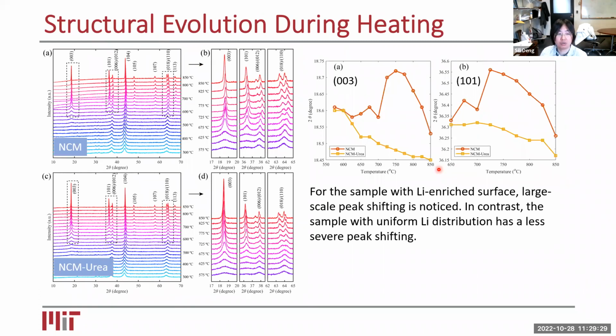We don't need to really go into the details, but this is to demonstrate how, after we utilize this method, the end product is sensitive to temperature. Because the whole reason for us to design this process is to push us to a higher temperature annealing process, such that we have hope to shrink the annealing time. And the purpose of this slide is to show you a thermal XRD, meaning that we do the XRD as we increase the temperature of the environment and see how sensitive the material is to the temperature.